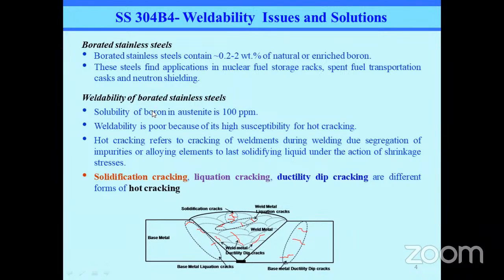In this case, the solubility of boron in austenite is only very negligible, that is around 100 ppm. So what happens is during this welding, material is melting and resolidifying. Because boron is insoluble in austenite, it gets segregated to the grain boundaries and interdendritic boundaries during solidification, and it forms low melting eutectics. That is, it forms some compounds that enlarge the freezing range of the metal. So when the freezing range is enlarged during solidification, there are a lot of shrinkage stresses acting on this weld metal, and because of this enlarged freezing range and shrinkage, the material is prone to crack, and this cracking is referred to as hot cracking.